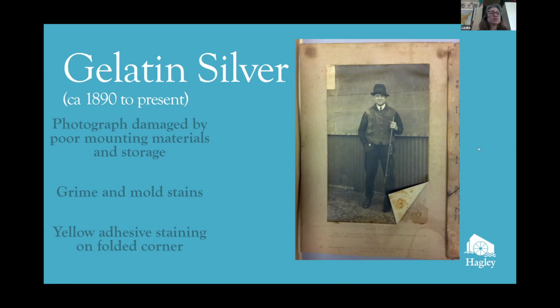The gelatin emulsion is also susceptible to mold if the humidity is high for a sustained period. The highlights may appear slightly yellowed as the gelatin ages and discolors with exposure to heat. Cracks in the paper and image layers can occur with careless handling or haphazard storage. The gelatin emulsion can also crack and flake if the photograph becomes very desiccated and dry.